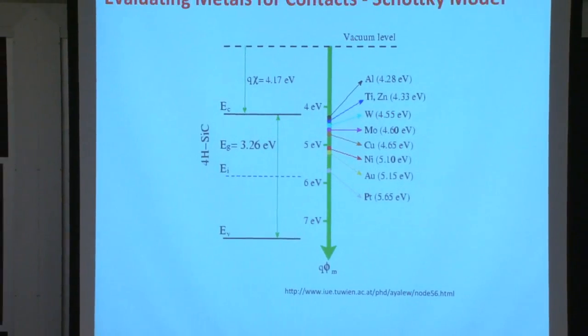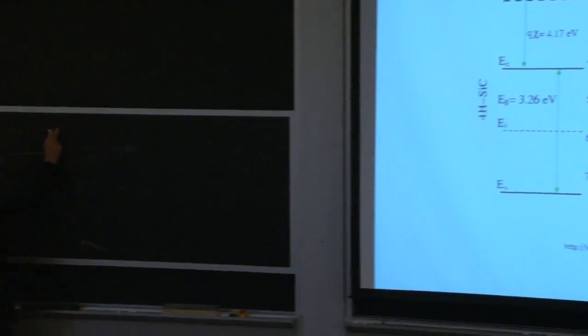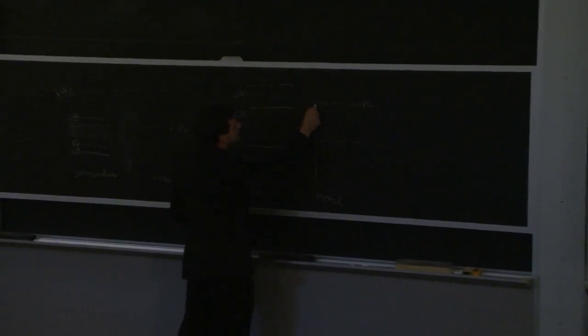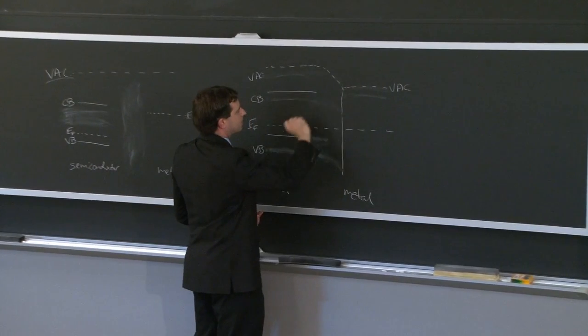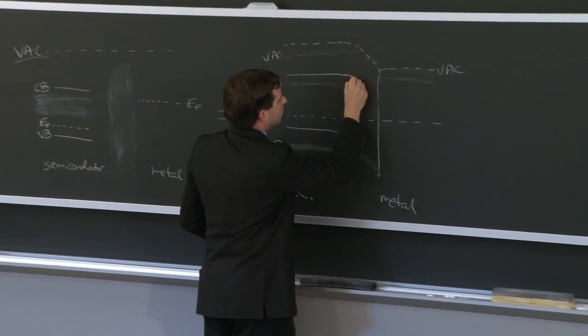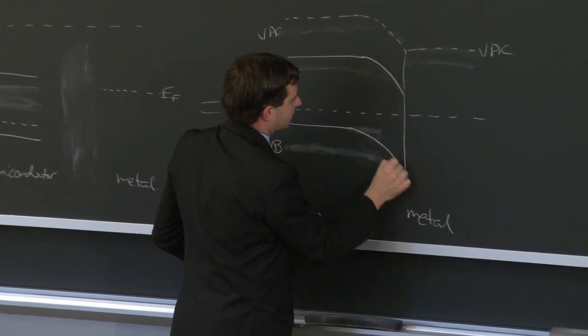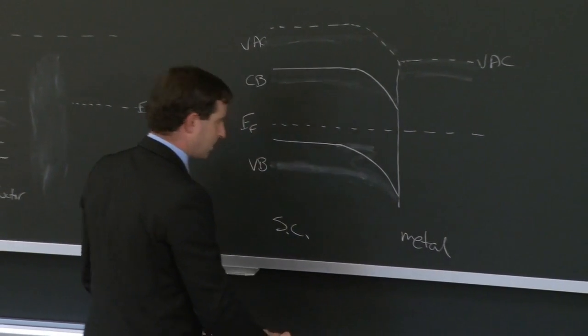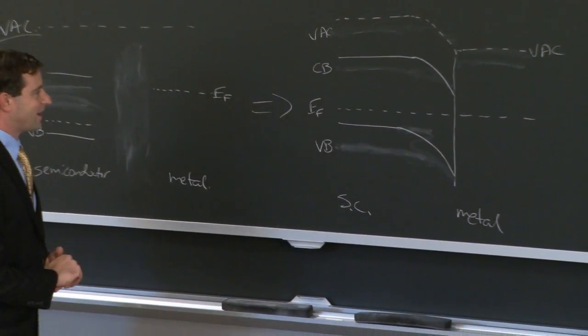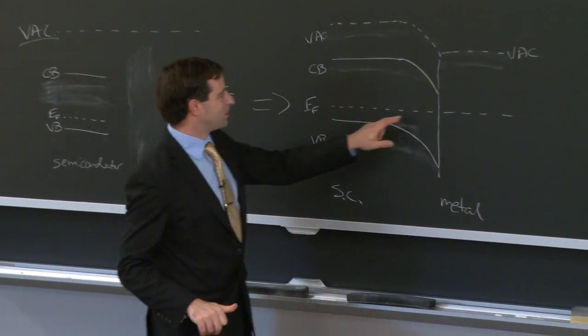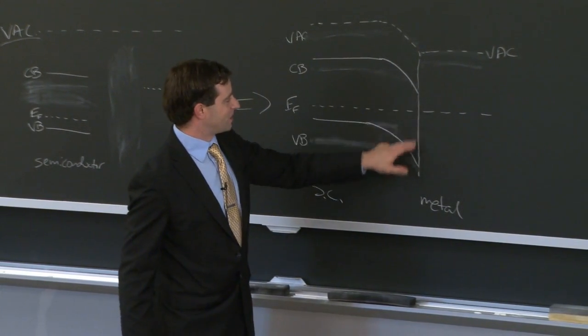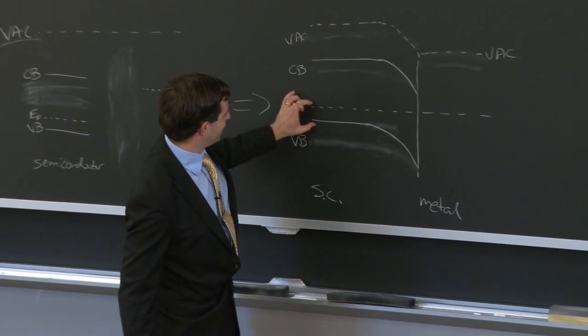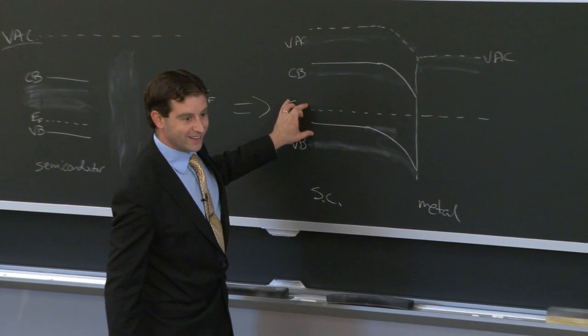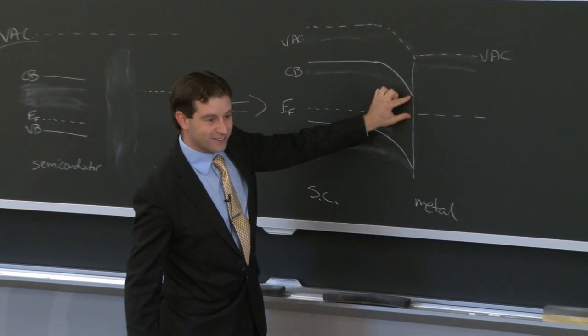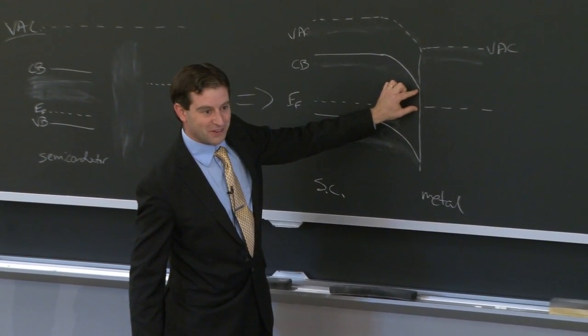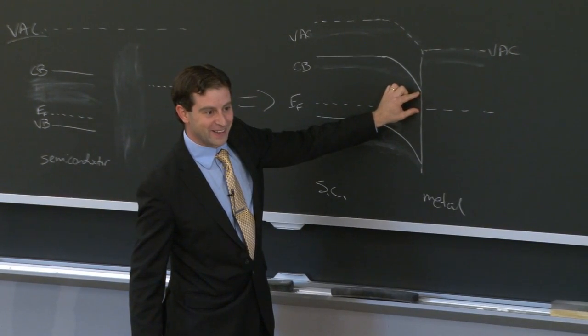So this is to say that we'll have a much more extreme bending here in the semiconductor than we will in the metal, virtually imperceptible there in the metal. And we drop this down as well. So some really interesting things have happened right here to the position of the Fermi energy within the band gap, right? Over here we have a P-type material, and over here, at the surface layer, it almost looks like this material is going N-type.